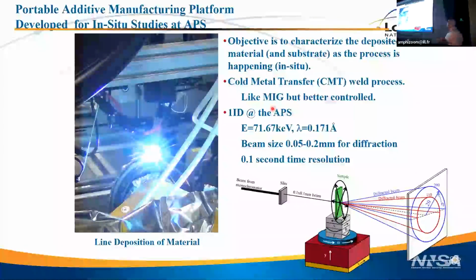The measurements were done at 1ID with about 72 keV X-rays. The beam size ranged from 50 microns to 200 microns, depending on what we were trying to do. And our best time resolution was about 1/10 of a second. That's fully set by the detector in two parts. It's one, the fastest the detector can read out, and two, because the material is somewhat grainy and we tend to saturate individual pixels. So this was not at all set by the flux at the APS.